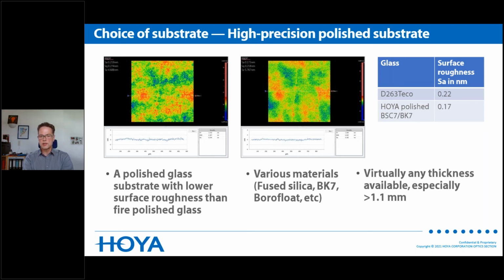And here the advantage again is that you can have the surface quality of fire polished glass with the thickness of any standard material, which can be larger than 1.1 millimeter to avoid the bending of the substrates.